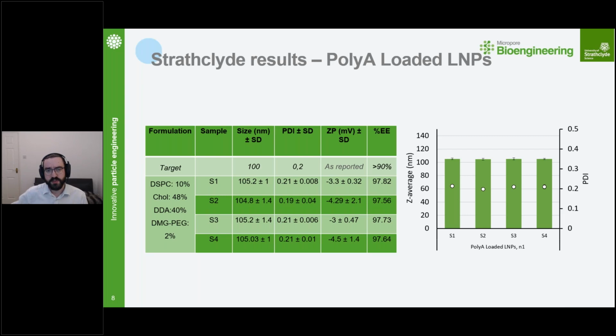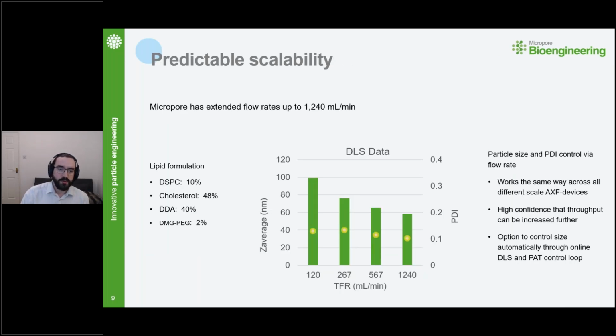And as you can see, for the 4 samples that we produced with the equipment, we were able to meet all of these targets and demonstrate that reproducible size control, very high encapsulation efficiency of 97%, and those low PDIs indicating that very high degree of control for the process as well, ranging from 0.19 to 0.21. We've then gone on to expand this. This is based on 500 milliliters a minute of material being produced, and we've been able to expand that initially lower down to 120, then upper to 1.2 liters a minute as well, all from one of those single AXF1 devices.